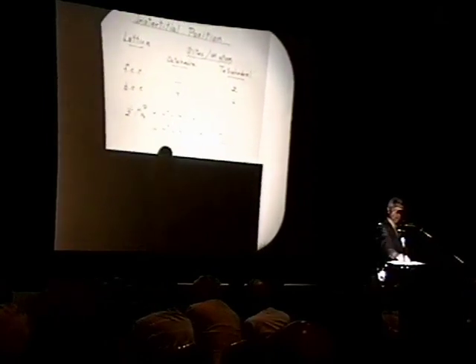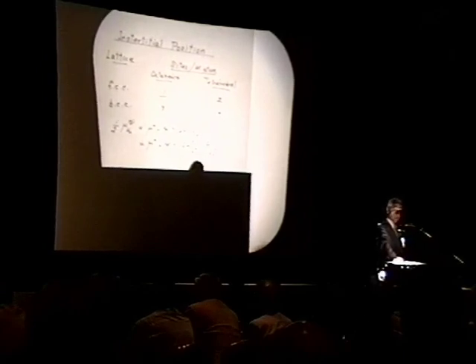What that does is that it forces one to use Fermi-Dirac statistics to express the chemical potential of the dissolved species. At equilibrium, therefore, you will have 1/2 the chemical potential of the hydrogen molecule equaling the chemical potential of the dissolved species, and you must express, in the general case, the activity of the dissolved species in this form. Gamma is the activity coefficient, theta is the degree of filling of the lowest energy category of interstitial sites of finite population.